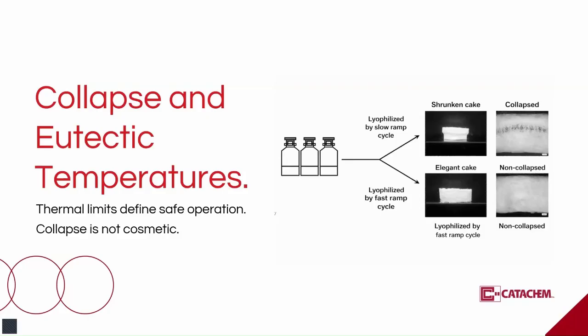There's also the glass transition temperature, TG, where an amorphous material shifts from a hard, brittle glass to a softer, rubbery state. Although close, the collapse temperature, where the freeze-dried cake actually caves in, is usually a few degrees higher than the glass transition temperature. Collapse is not just cosmetic. Cake collapse is a physical signal that the product matrix exceeded its structural limit during drying.